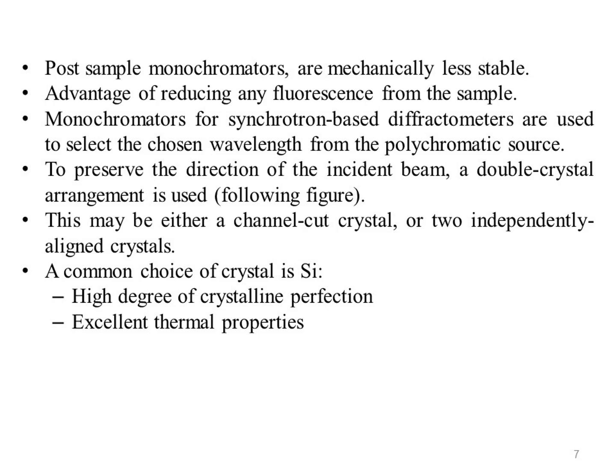A common choice of crystal is silicon, because of its very high degree of crystalline perfection and its excellent thermal properties in the intense synchrotron beam.